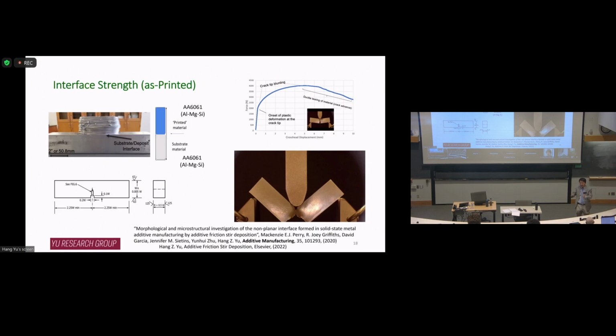So my beam is not small. It's not a micro scale. Essentially, it's a 10 centimeter long beam. But still, because the aluminum alloy has a relatively low strength and my interface is relatively strong, we don't have a valid K1C measurement. But from that, we can semi-quantitatively, or qualitatively, say that my interface is pretty strong. That's a really good thing about this, because of the mixing and the cold plastic deformation, I got a good interface, and also we have fully dense deposition.